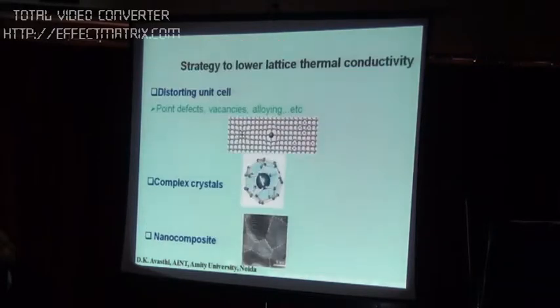So how can one do it? This can be achieved by distorting the cells. That means you introduce point defects and vacancies and do alloying. If these kinds of defects are there, then one can lower the thermal conductivity. Or you take complex crystals like this, which have rattling molecules. In these, you also have a lot of electron phonon scattering and lower thermal conductivity. Or you use nanocomposites in nanostructure form, where you also have lower thermal conductivity.